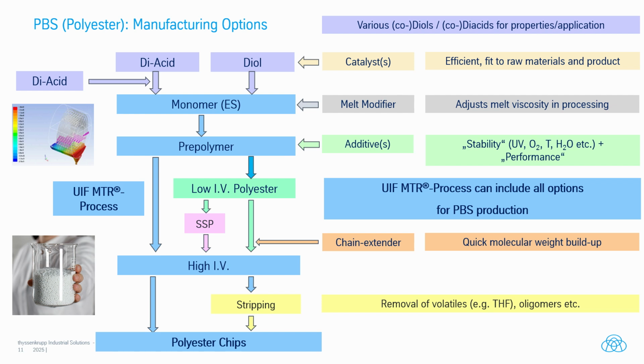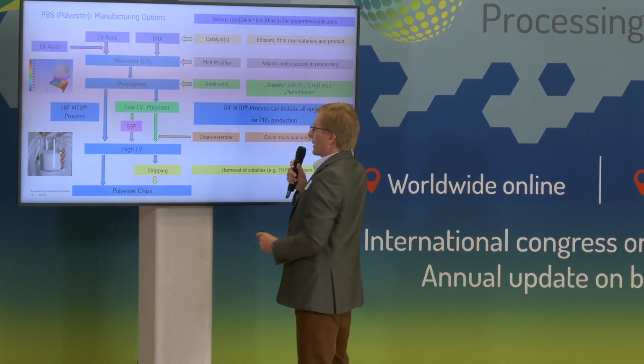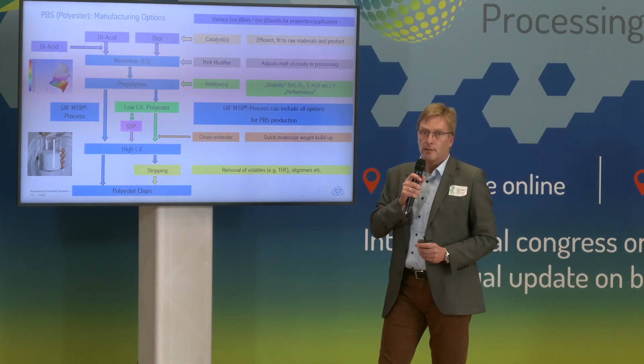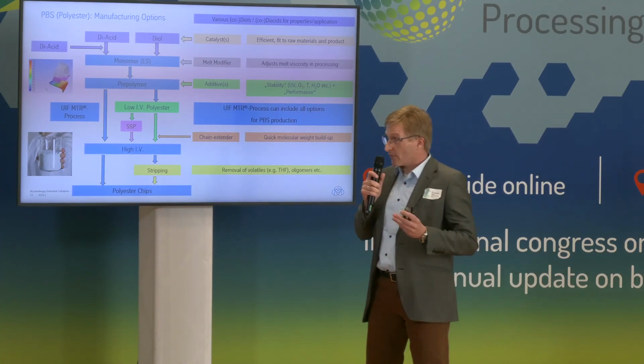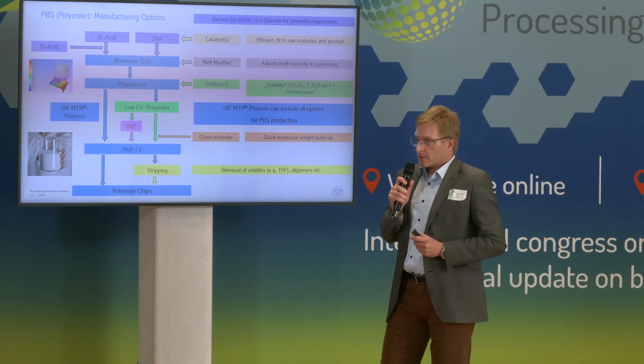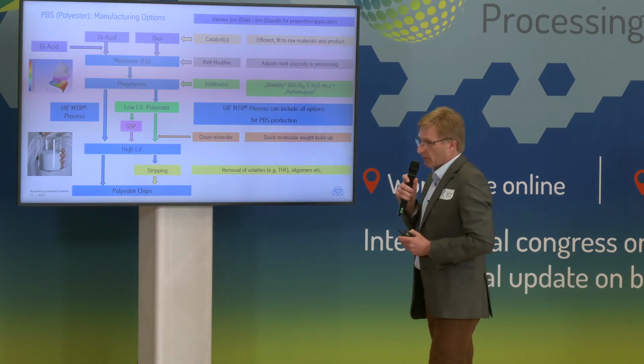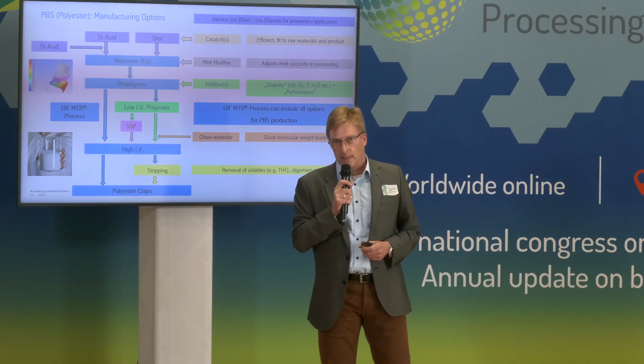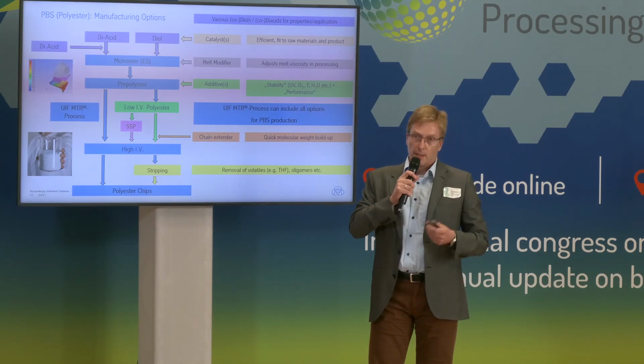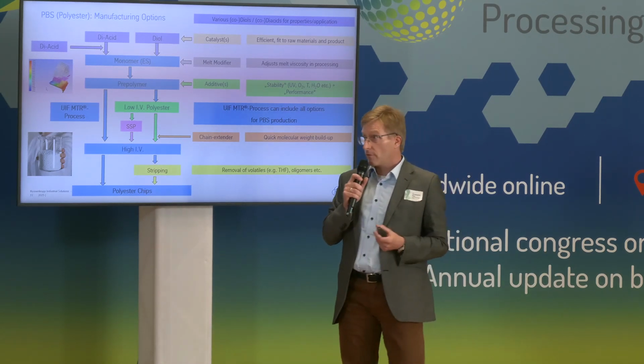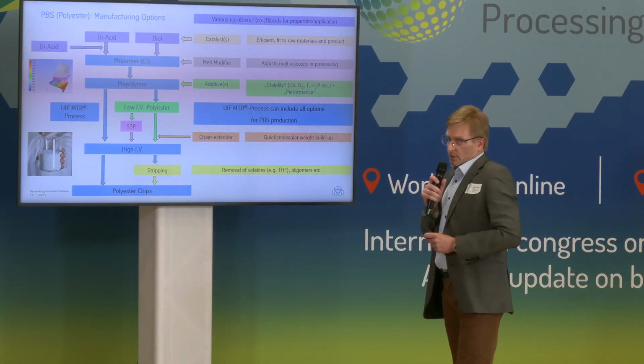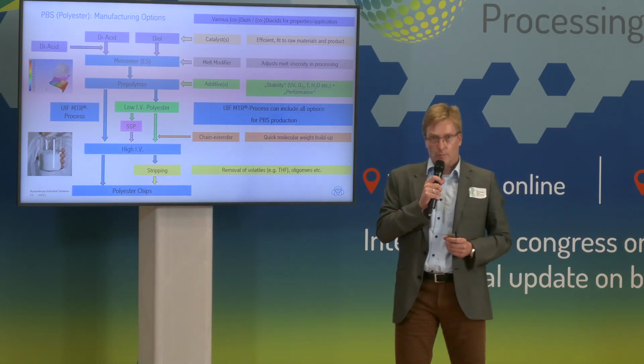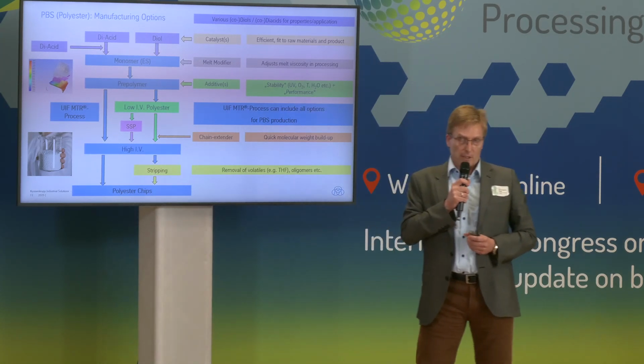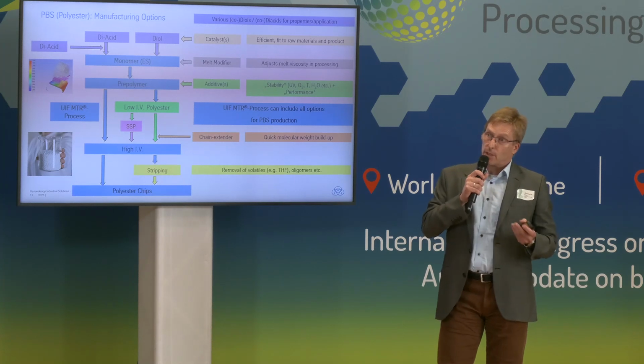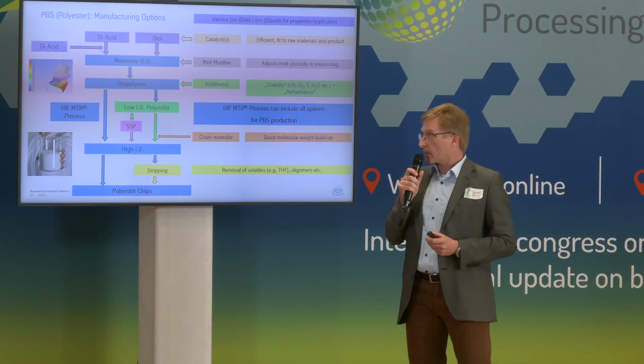Then you should have a good idea what type of catalyst you want to use. The catalyst is required to produce a monomer in esterification. After you've made the monomer, you should think if you want to functionalize this monomer. Especially here, some melt modifiers could be added. Melt modifiers like tri- or tetrafunctional components like pentaerythritol to modify later on the melt viscosity, which is required especially in injection molding. You don't want to have too high melt viscosity in injection molding, but on the other hand, you want to have a high molecular weight.